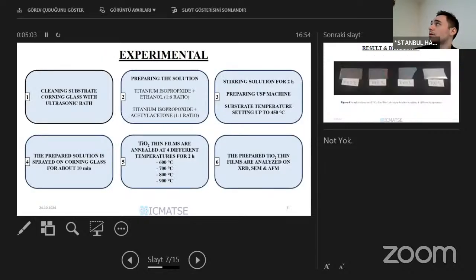There is an experimental chart with about 6 main steps. In the first step, we use a Corning glass, which shows good properties at higher temperatures, and we should first clean the substrate — clean the glass in an ultrasonic bath. After cleaning the glasses, we need a solution, because this ultrasonic spray pyrolysis technique requires one.